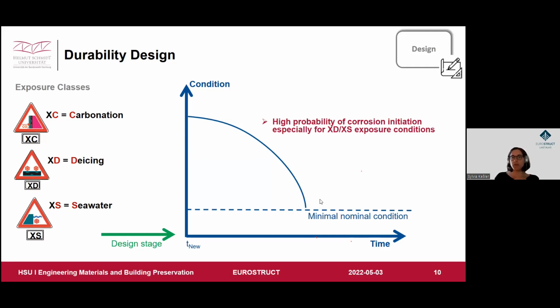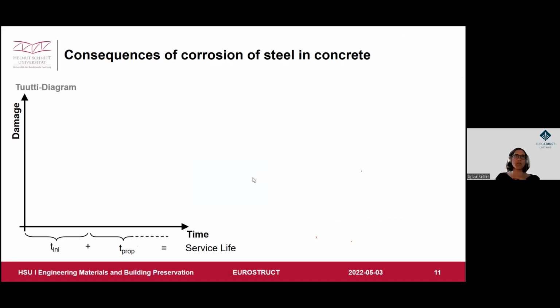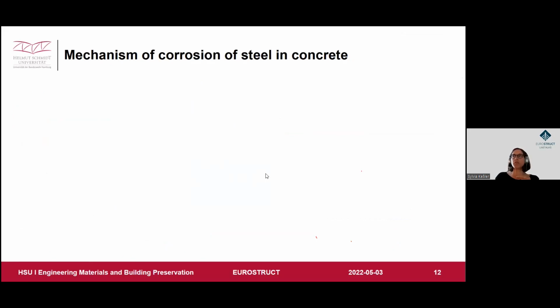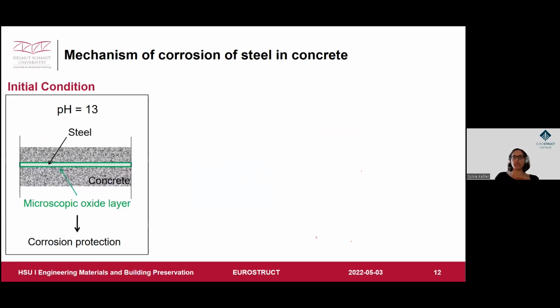So what is really the mechanism when we look at reinforcement corrosion? You have probably seen the 2D diagram several times already, so that we have the initiation phase and we have the propagation phase. And the initiation phase ends with the depassivation of the reinforcement. And here I bring you some comparable sketches, because normally the concrete provides a high alkalinity, which leads to the formation of a microscopic oxide layer. And with this passive film, as we call it, we have corrosion protection.